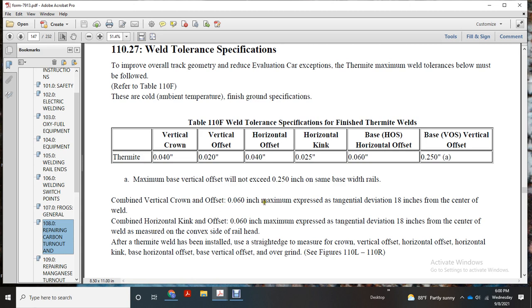Combined vertical crown offset with a 0.060 inch maximum express tangential deviation 18 inches from the center of the weld. Combined horizontal kink offset with a 0.060 inch maximum express tangential deviation 18 inches from the center of the weld. Measure from the convex side of the railhead.